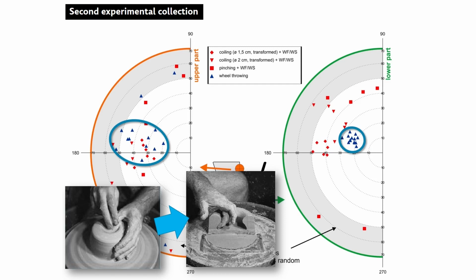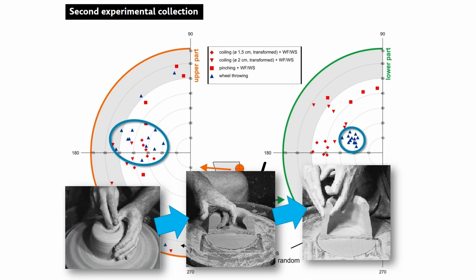The preparation of the base before lifting requires strong deformation of the clay at the base of the wall, when the potter transforms the lump of clay into the form prepared for lifting. While she or he lifts the clay mass upward, the rest of the clay is lifted above the fingers but is not affected by their movements, and thus the rim itself, the last remnant of the clay, is practically unaffected by the lifting movement.